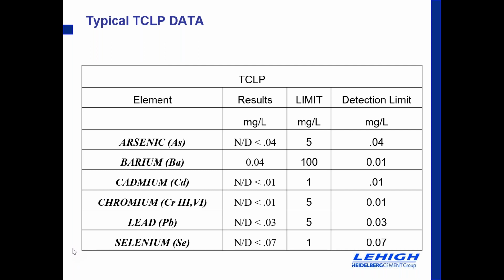I would also add that one of the elements we're missing here that has come up and we've gotten some attention over the last 5 years is aluminum. Aluminum is not a heavy metal. It's one of the most abundant metals in the Earth's crust, and it's very light. So typically it was not viewed as a target element. Now there is some discussion about aluminum and toxicity and potentially contributing to Alzheimer's and other things, but that data is still a work in progress. We don't test for it. In some of the sites we're at, in the test wells, they do monitor it, and when the job is done right and we've tied up the soils appropriately, we don't see anything moving through the ground because of the very low permeability we've achieved with slag cement.